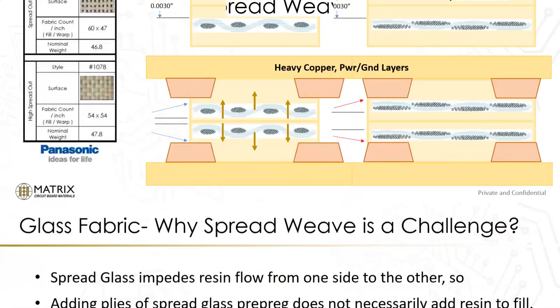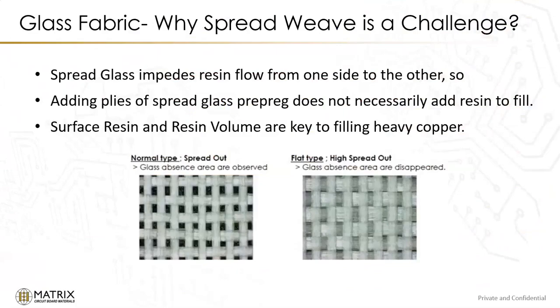So my part is, why is the spread weave a challenge? Well, because the spread glass impedes that resin flow from one side to the other. That's really the main purpose of that. And I don't see as much of a benefit by adding more plies because of the spread glass. It doesn't necessarily add more resin where we really need it to be in the fill area between those copper features. So the surface resin and the resin that's available for filling the volume there are really the key with these lower flowing resin systems with spread glass to filling that heavy copper.